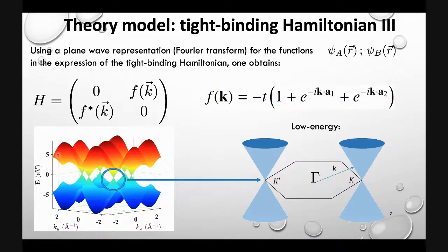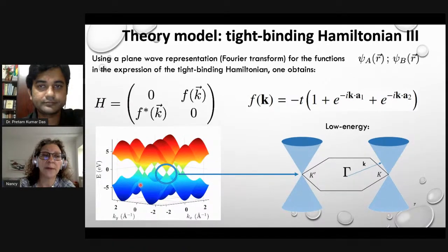And the modulus of this function, when I plot it, has this particular form, with which probably some of you are familiar, having seen works on graphene. Now, what makes this shape special is the fact that the red part, which is the positive energy, or what we know as the conduction band, where the electrons can move freely, touches the blue part, which is the valence band, where the electrons are tightly sitting in their own positions and don't move. They are connected in bonds with the other electrons coming from the other atoms in the lattice. These two conduction and valence bands touch at a series of discrete points. In fact, they touch at 6 separate points.